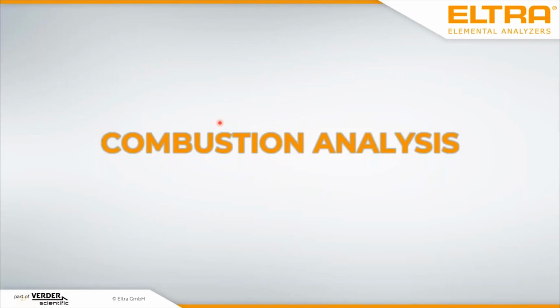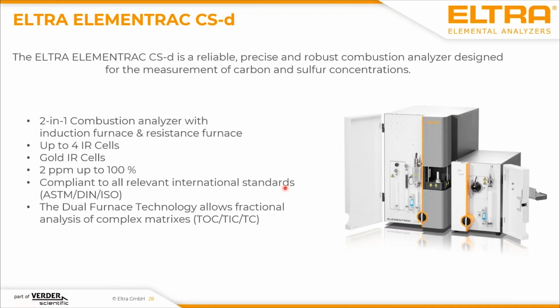The main part, what ELTRA is doing, is the combustion analysis. And combustion analysis means that you heat up your sample in an oxygen stream. And we see this here, for example. We have here our CSD. The D is for dual carbon sulfur analyzer with a dual furnace. So we have two furnaces inside this analyzer. So a 2-in-1 combustion analyzer with an induction furnace and a resistance furnace. The detection method itself is the same for both types of furnaces. So it's infrared detection, which is the most common method for this type of samples.